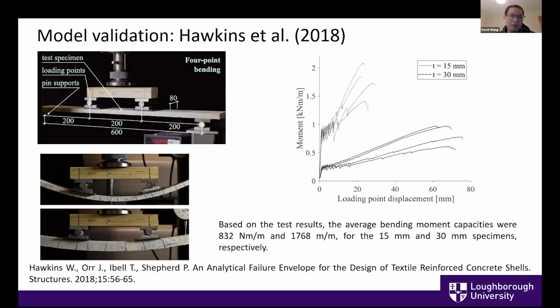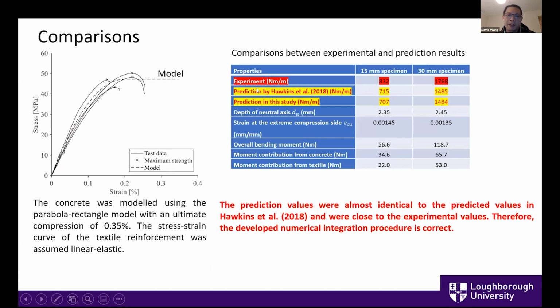In order to validate our modeling procedure, we first did some model validations with some people's experimental work, which is for cast concrete. They have two different loading cases. For the first loading case, our simulation result is 707 Newton meter per meter. For their prediction, 715. Both our prediction and their prediction are slightly less than the experimental values. Same conclusion for the other loading case.